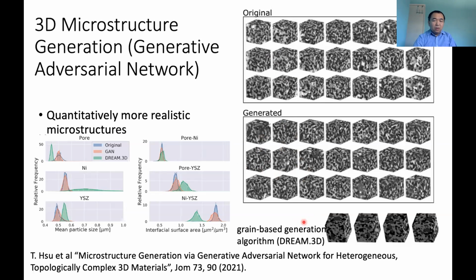So for more quantitative analysis of Tim's results, look at, for example, the mean particle size distribution and the interface surface area distribution of the original and neural network generated 3D fine microstructures. And they align very well and compare favorably with the results of Dream3D, which is the green distribution. So this is a very impressive work.